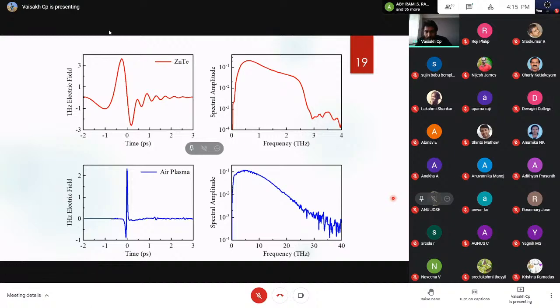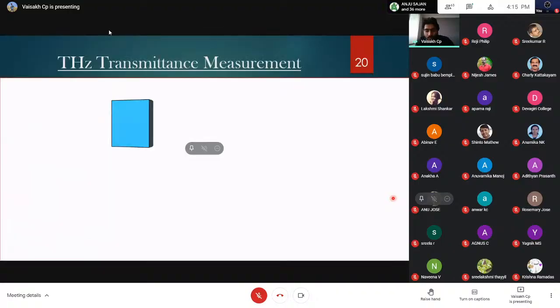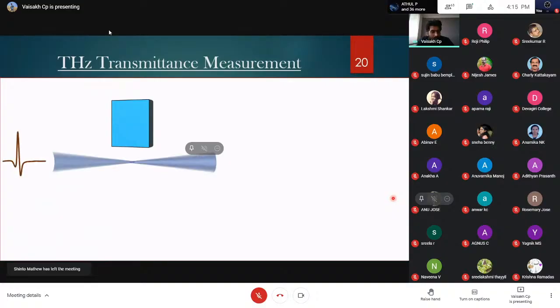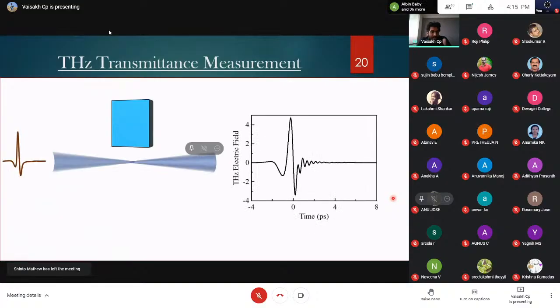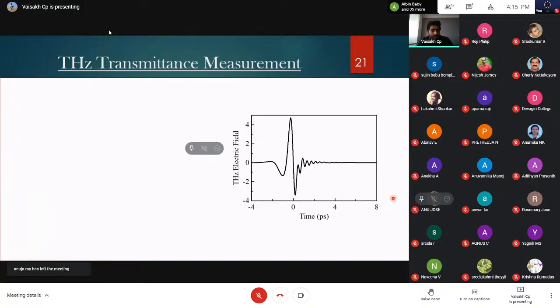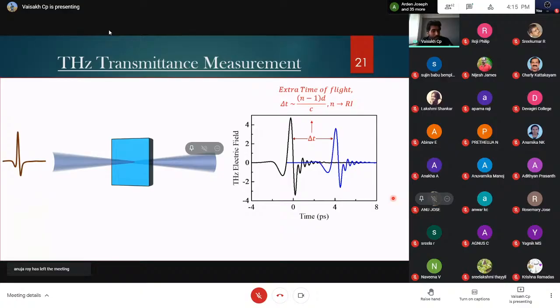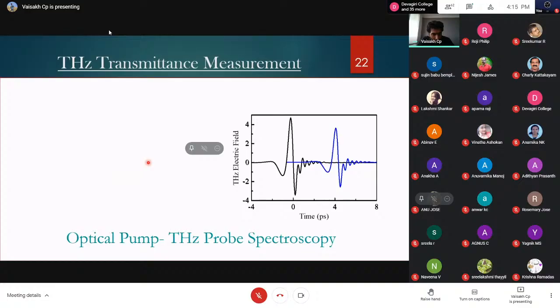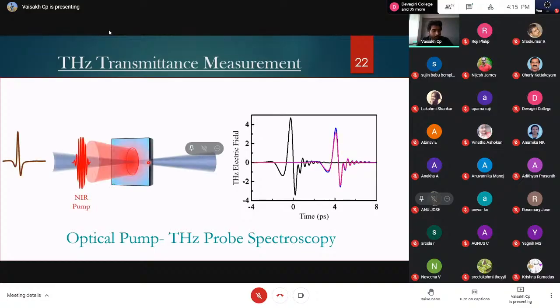So now that we have terahertz radiation at our disposal, the next thing to do is to pass it through matter. One could just pass it through air and see what the spectrum looks like. With that as a reference, one could pass it through materials that we want to study. You can see that when you have a thick sample in the path, the pulse shifts by a delta T amount, which depends on the refractive index of the material and the thickness of the substrate we use. And one could do a similar experiment